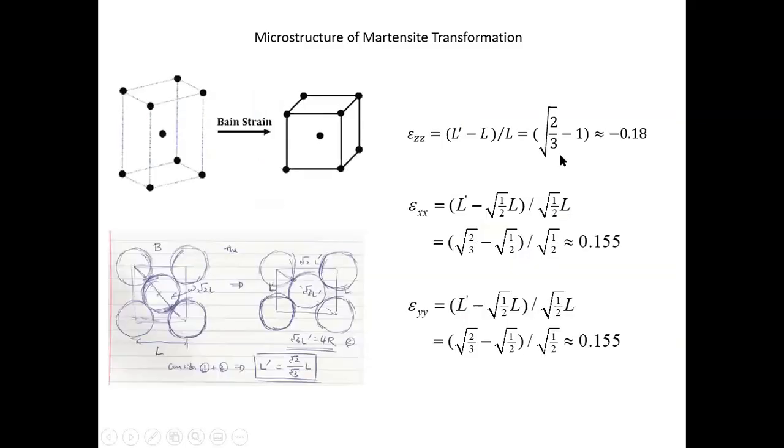Okay, so now if this is clear, the thing we want to do is find out exactly how we stretch each edge or compress each edge in order to achieve that particular deformation, right? So now I'm writing down the numbers for you again. For this one, I have L prime, the length of all the edges and heights for the box, which is square root of 2/3 times L. And for this original FCC box, I have the height equals L.